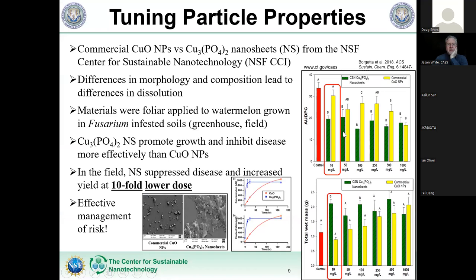At this point I joined the NSF Center for Sustainable Nanotechnology — now in year eight of thirteen, a project of nearly $40 million across eleven universities with about fifty graduate students and postdocs. Being a chemistry center, we focused on whether you can tune the properties of copper during synthesis to produce different morphologies and behaviors, and then optimize your impact. A 2018 paper compared commercial copper oxide to custom-synthesized copper phosphate nanosheets — changing both composition by including phosphate and morphology by making a sheet instead of a sphere. The answer is yes, you can tune it.